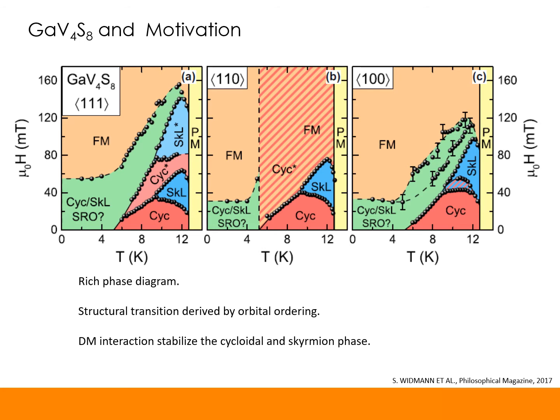Although there is certain literature available which talks about the static structure of these materials, there is very limited work which explains the dynamic structure. The absence of such studies is due to the inability to get larger single crystals of this material, which scatter an inadequate amount of neutrons, showing some dynamic structure in the system. So my motivation is to look into the dynamic structure to understand the spin interactions between the neighboring magnetic vanadium ions.